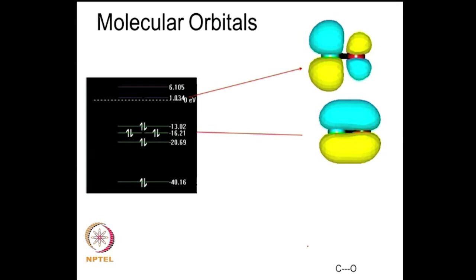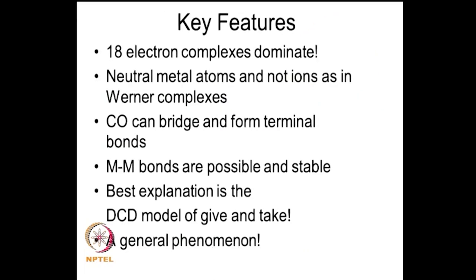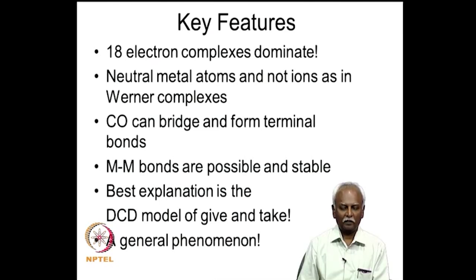So, let us just summarize some of the aspects that we have learnt in metal carbonyl chemistry. These are the key features that we have encountered in today's lecture. First of all, 18 electron complexes appear to dominate. There are very few complexes in which you have more than or less than 18 electrons. You also encountered the fact that neutral metal atoms, and not ions, are encountered, whereas in Werner complexes, mostly they are charged systems. And thirdly, carbon monoxide can form both terminal and bridging carbon monoxide units. And also, we encountered several systems where there are metal-metal bonds, even when there are no bridging ligands. This is again uncommon in Werner's chemistry.